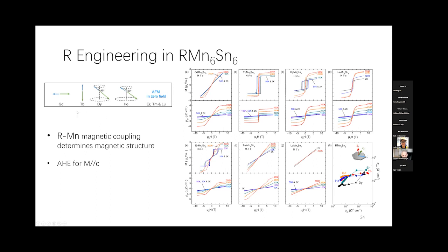As I said before, the rare earths and magnetism, the magnetic coupling, determine the magnetic structure. So interesting, if your rare earths are changing from gadolinium to holmium to erbium, finally this compound becomes antiferromagnetic at zero temperature. So the very special thing is the erbium 166. If you apply a magnetic field, the compound will become spin polarized. At the same time, you see a clear anomalous Hall effect in this compound.